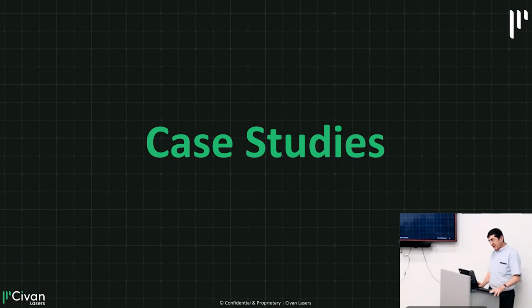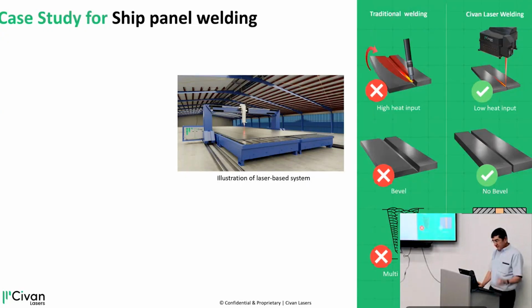So now I'll show you a few case studies. First of all, in deep penetration, this is an example of welding of ship panels. If you do it in the traditional way, let's say if you have here an inch of weld that you have to do, first of all, when you do it with a torch, you have to put a huge amount of energy, and there's a very big heat affected zone. The energy goes to the side as well. You have to prepare a bevel here.